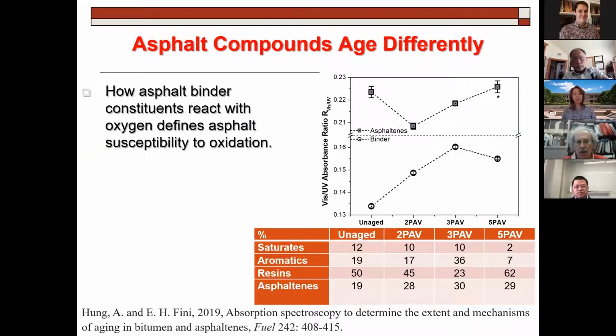Remember I said, what if our asphalt never goes away? What if we never have to repair a road or never have a pothole? Well, the reason we do have potholes, the reason we have to dig it up, mill it, and dump it or dispose of it, is because it gets worse and worse with aging. Part of aging is oxidation. I'm showing you the elements of asphalt here, the same thing as showed: saturate, aromatic, resin, and asphaltene. Then you see in the table.